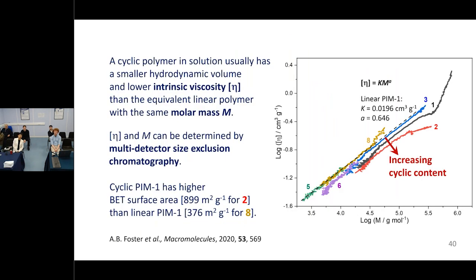A way of getting a bit more information is by looking at Mark-Houwink plots. These are plots of the log of the intrinsic viscosity against the log of the molar mass. You can get these these days out of size exclusion chromatography, where you have additional detectors. You have a light scattering detector, which gives you an absolute molecular weight without calibration, and a viscosity detector, which tells you what your intrinsic viscosity is.